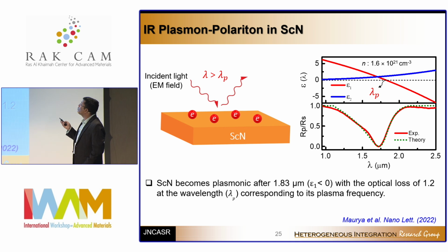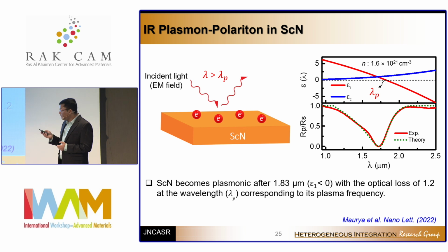Because it has a carrier concentration of 1.6 × 10^21, you see the plasmon resonance, the ENZ frequency, at around 1.8 micrometer. 1.8 micrometer is very close to the telecommunication wavelength of 1.5 micrometer. So it's extremely interesting and extremely important.